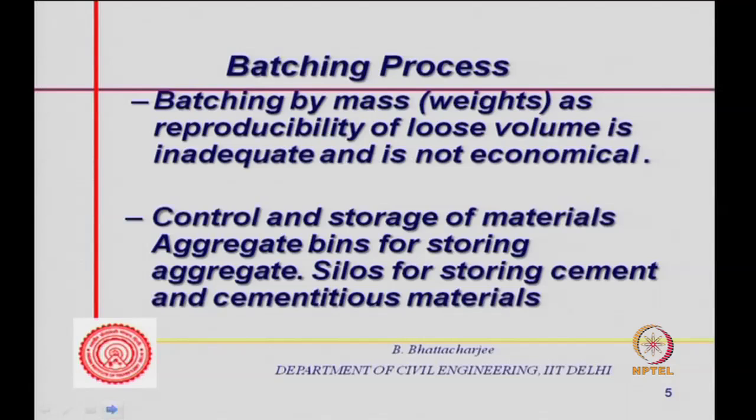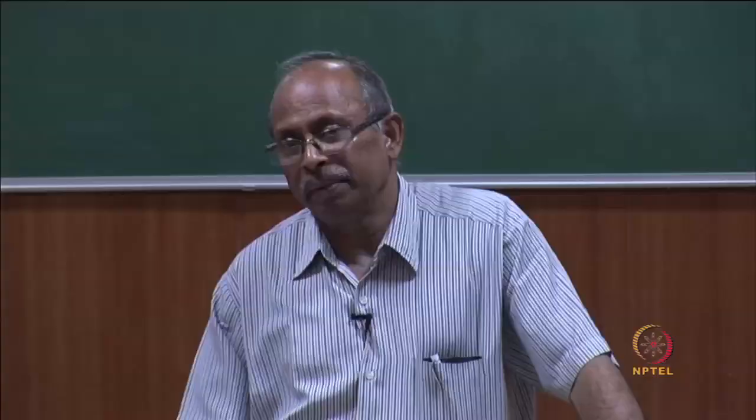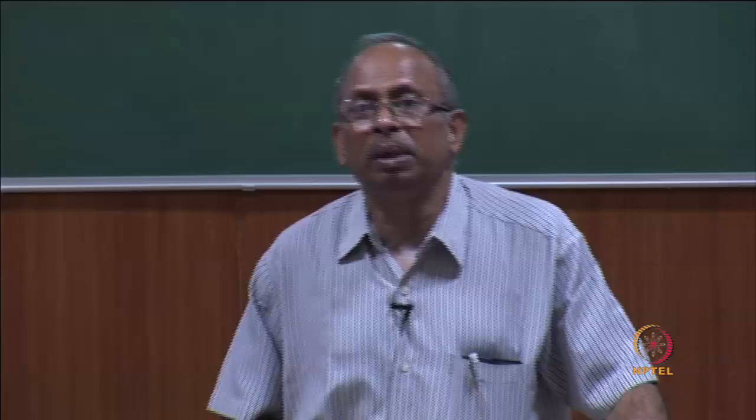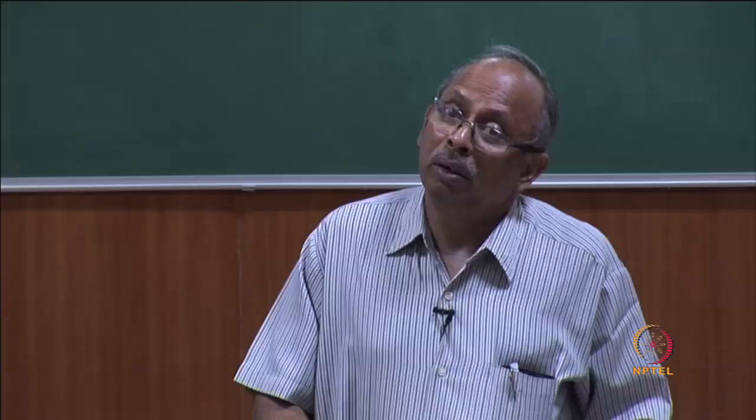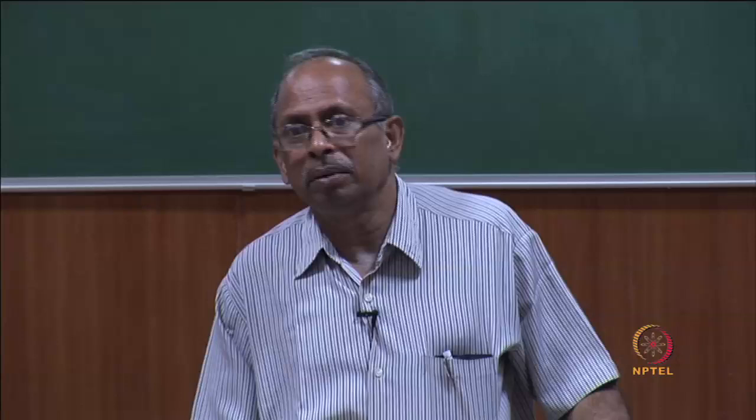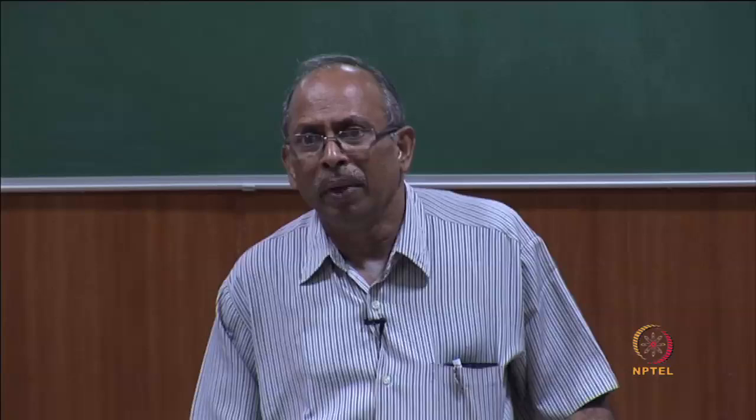Then, control and storage of materials. You must have aggregate bins for storing aggregate, and silos for storing cement and cementitious material. Actually, storing is very important. Aggregates should not get contaminated with dust or something of that kind. Apparently it may look simple, but if you store it in the open, you can have problems of dust coming from the environment and contaminating them, especially in places like northwest India, where dust storms are quite common in summer, like Rajasthan, even places like Delhi, Kanpur. Storing aggregates in the open may be a problem.